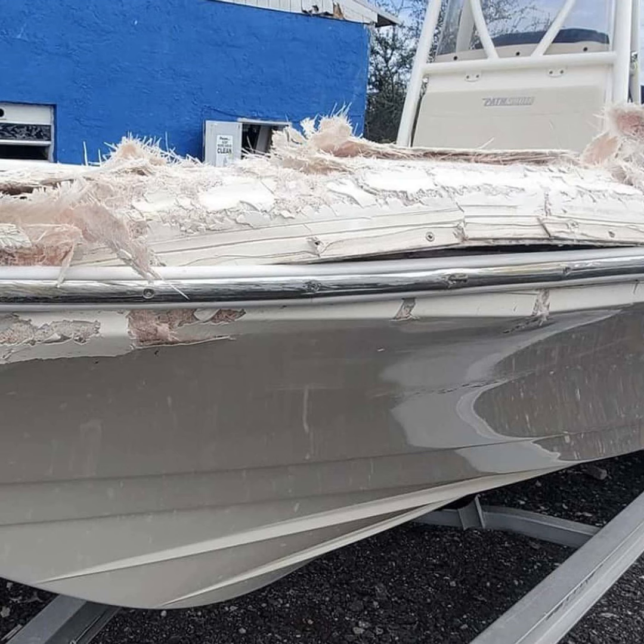One of the big differences that you're going to notice between epoxy and the polyester or vinyl ester based resins is that the poly and vinyl kick on a percentage, a 1 to 3% range. Really, vinyl ester, it's recommended that you don't go under 2%. And I don't recommend much going over 2% either. 2% is pretty much the happy spot for vinyl ester. But when you're looking at epoxy resins, they're going to be measured on a ratio. So it's going to be like a 2 to 1, 3 to 1, 4 to 1 kind of thing. 3 to 1 is pretty common.